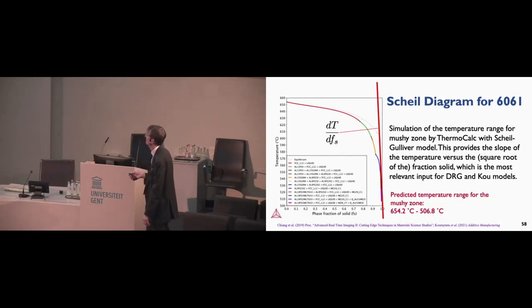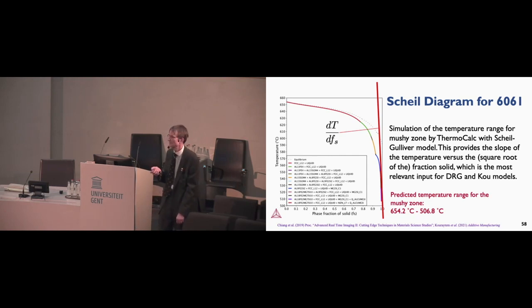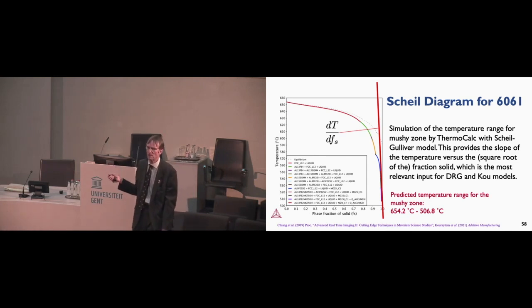We took a look in the literature at what models there are. And of course, there's the famous DRG model. Most of these models, Kou's models, or various variants of them, look mainly at the solidification sequence. And so 6061 is a material that freezes sort of gradually. Then near the end of solidification, the rate of change of temperature with respect to solid fraction gets very steep. And that's bad news, because that means that your mushy zone develops these long, long, skinny bits of liquid that are very difficult to feed. And that's a lot about where the cracking comes from.